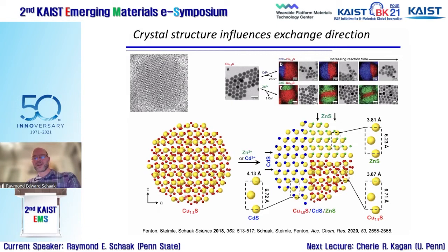So what ends up happening, if you think about at the atomic level, what happens when you do a cation exchange reaction starting with copper sulfide and replacing some of the copper 1 plus cations with, let's say, cadmium 2 plus? You end up getting a certain number of cadmium 2 plus cations in here, which is basically saying you get little regions of cadmium sulfide in a matrix of copper sulfide. The problem with that is cadmium sulfide and copper sulfide are not miscible. They don't want to form kind of a solid solution, if you will. They want to remain segregated. They want to remain separate.